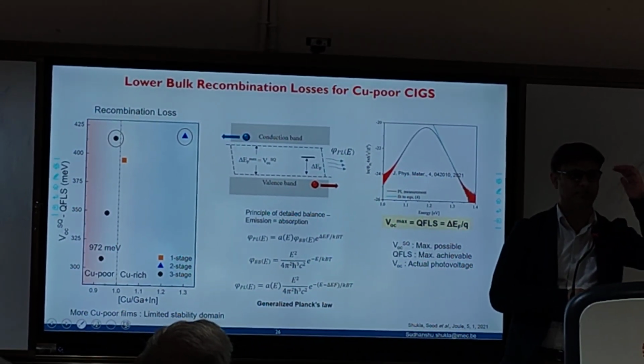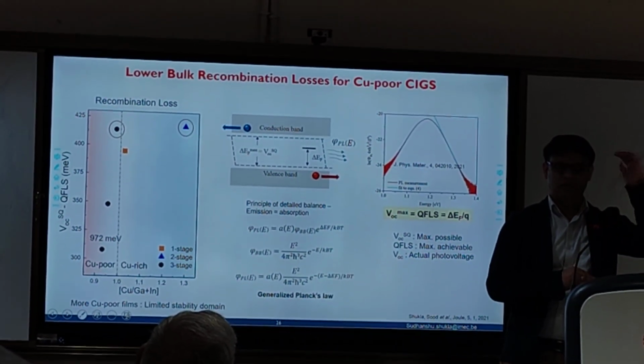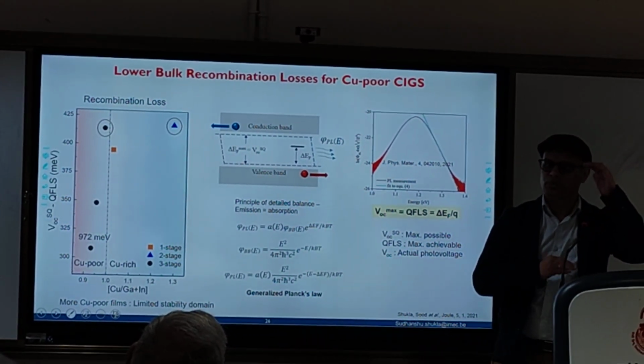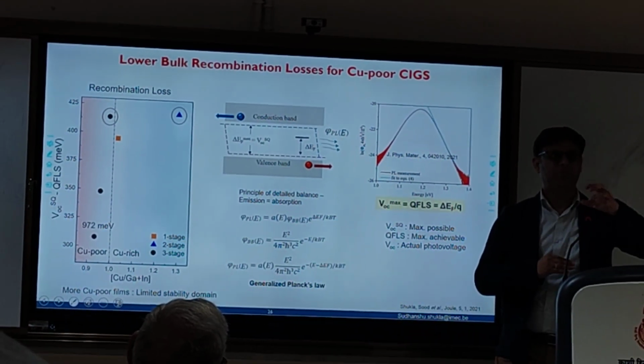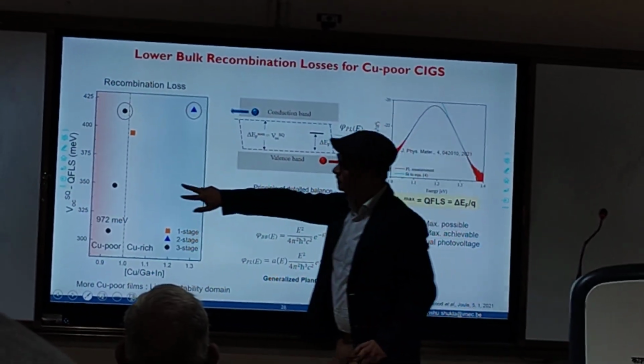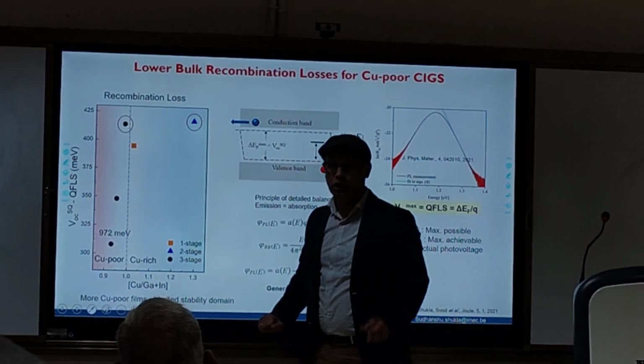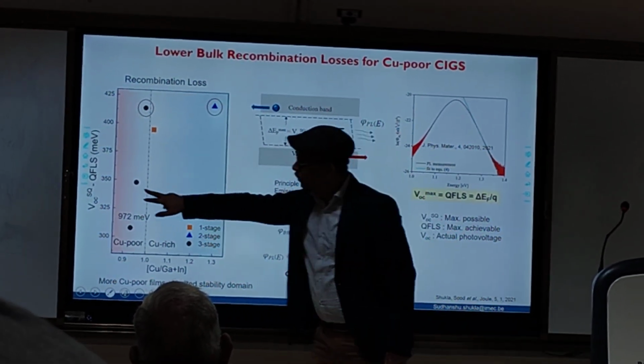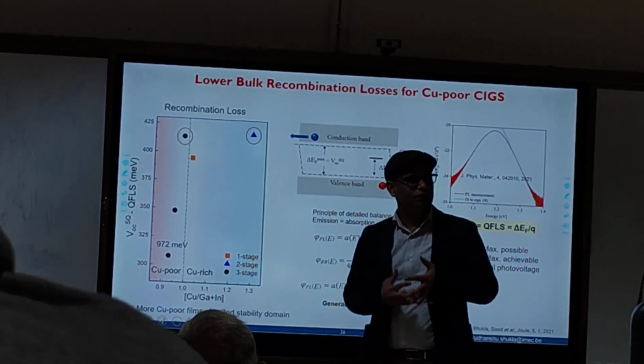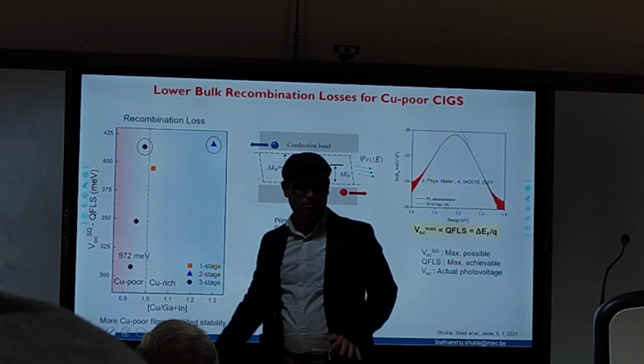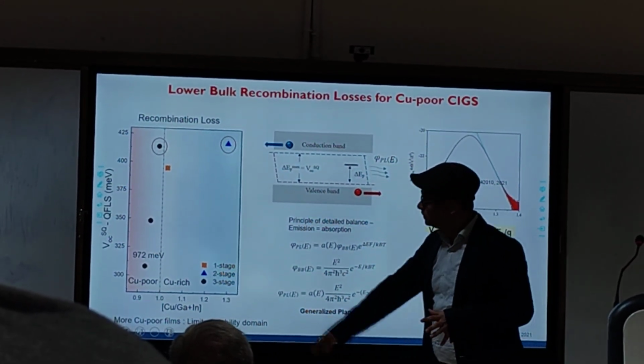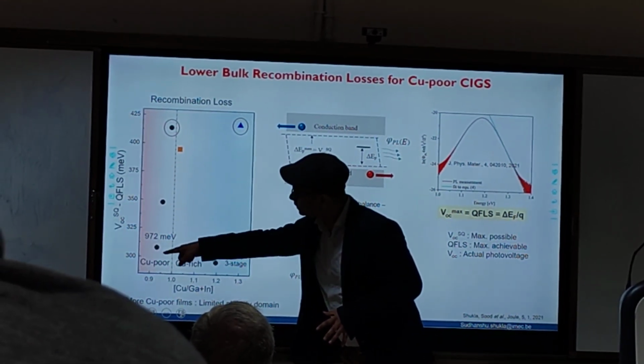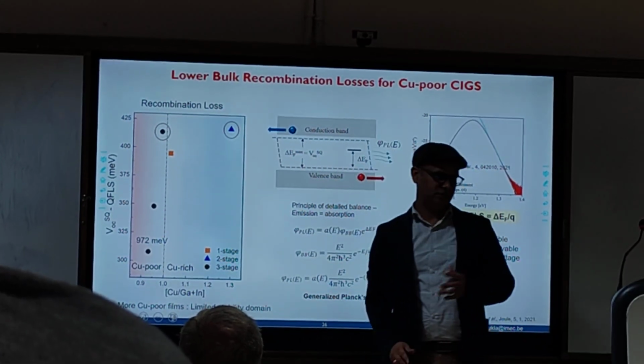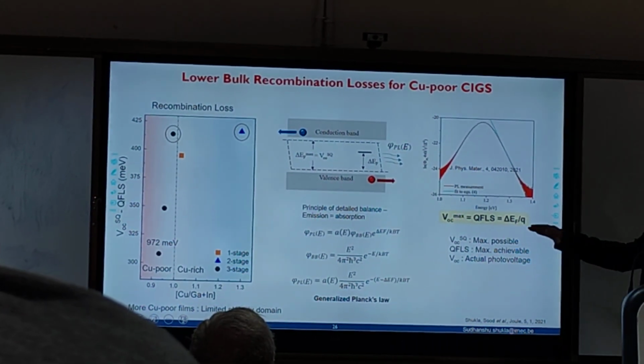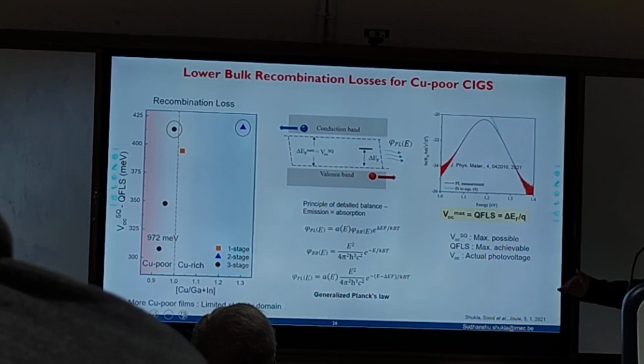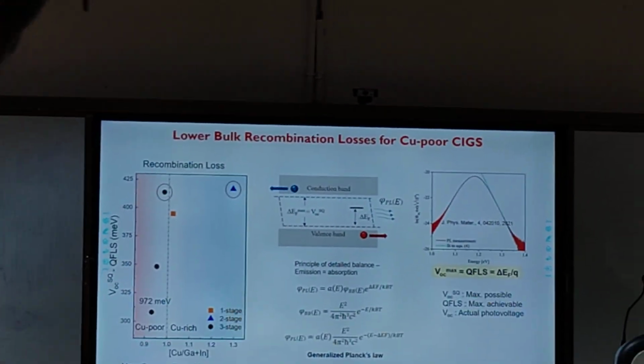It's called the Shockley-Queisser limit. Don't have the time to go into what the Queisser limit is, but it actually poses a fundamental limit governed by thermodynamics. So the difference of this tells you the loss in the material. The lower this number, the better it is. The closer you are to the theoretical number, the better it is for your device. So as you see, if you go from copper rich to copper poor, the number decreases, and this is actually nothing but because of the fact that we reduce the recombination. And that's why it is happening.